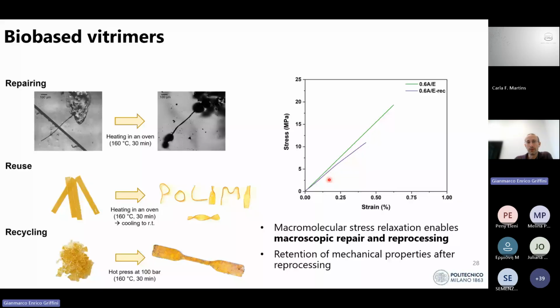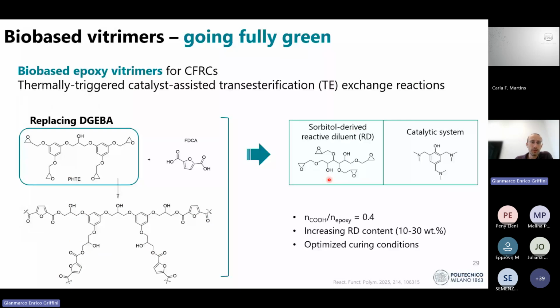Now, this was, let's say, the first step towards a fully bio-based system, which we then tackled by also substituting the bisphenol A epoxy derivative with an algae-based epoxy system, glycerol-based. Again, using FDCA as a co-monomer, we obtain a three-dimensional network that was also additionally formulated with a reactive diluent to make the system a little bit more processable and more easily usable as a resin for composites.